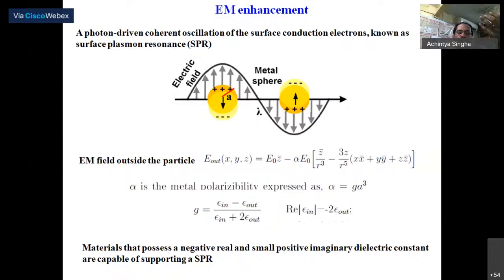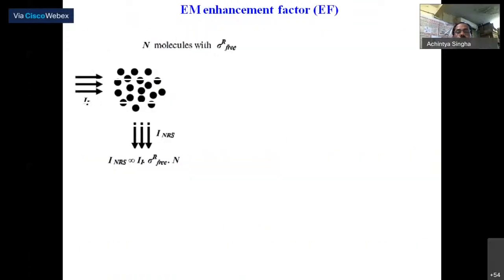What is the reason behind this huge electromagnetic enhancement? We know that a plasmon is the coherent oscillation of a metal nanoparticle's electrons due to interaction with the electromagnetic field. Due to the interaction of this plasmon with the electromagnetic field, it localizes an electric field on the surface, and that localized electric field excites the molecule adsorbed on the surface. So that will enhance the Raman signal.